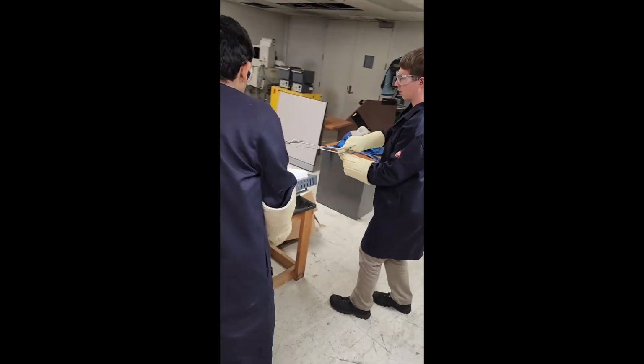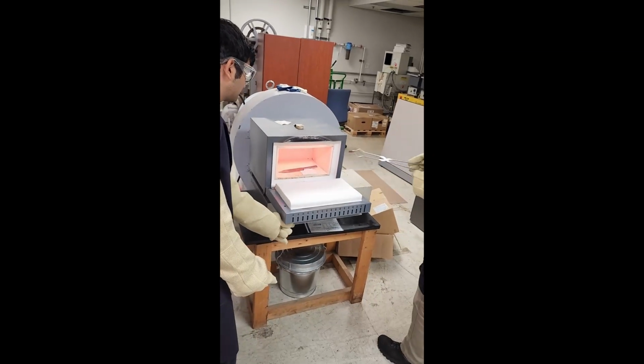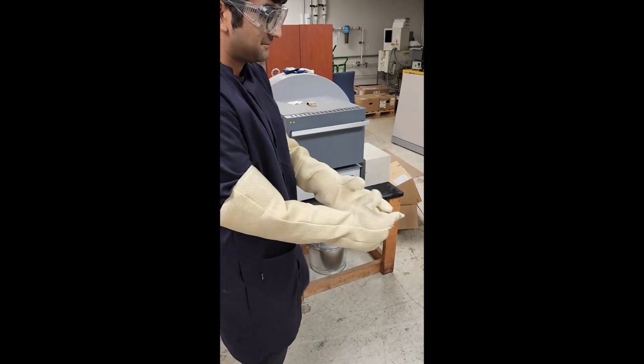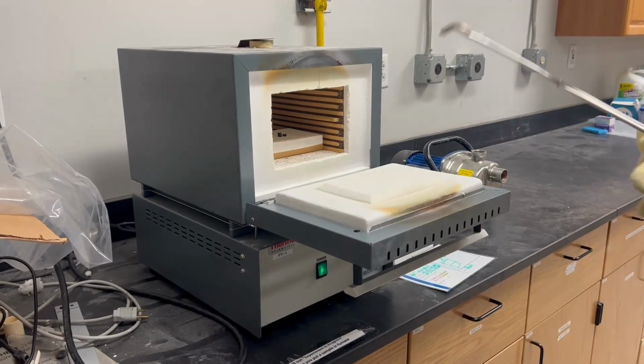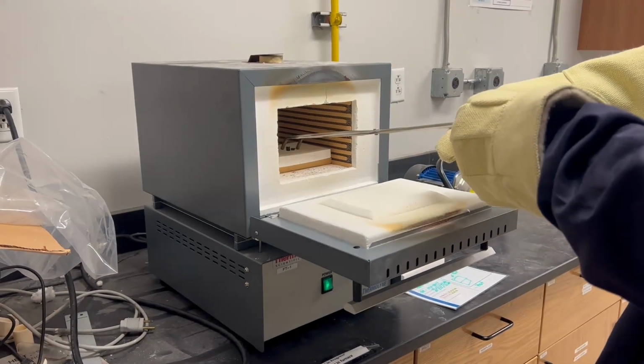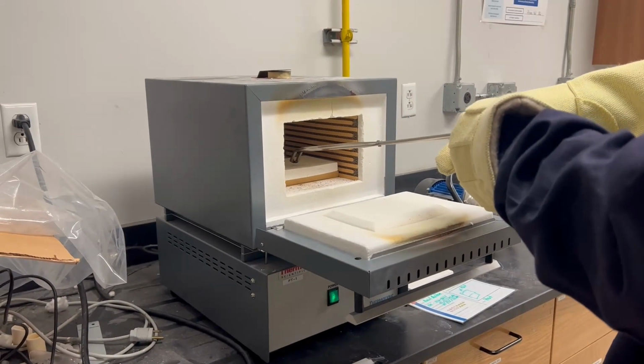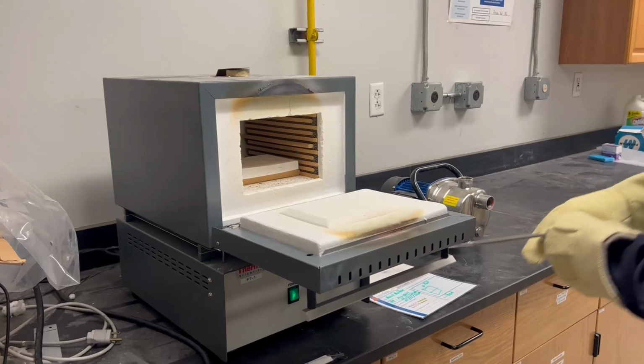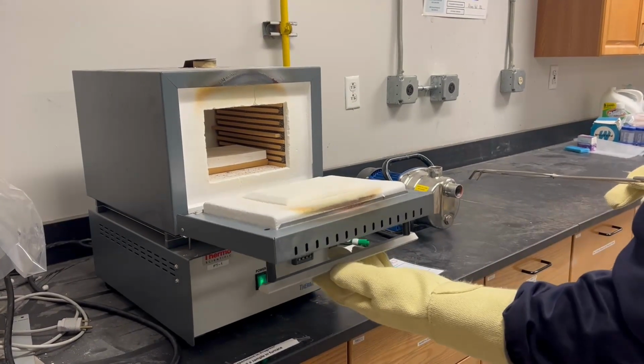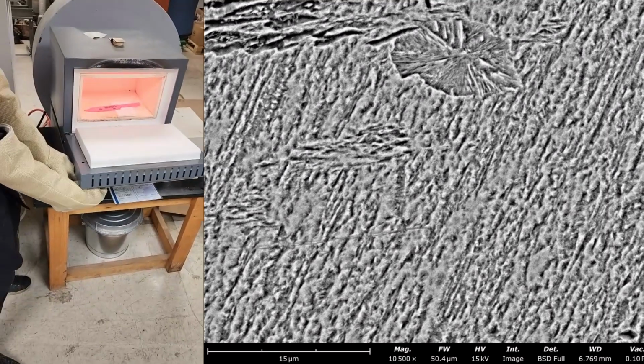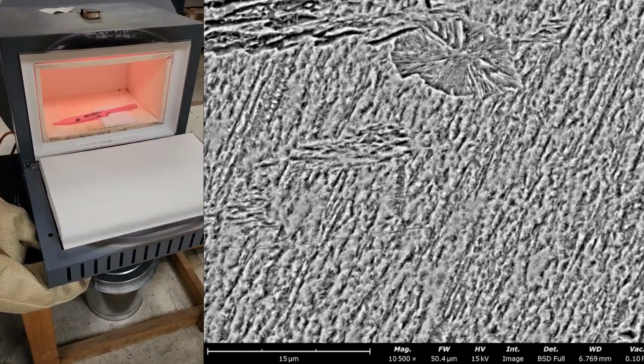As we moved into heat treatment, we wanted to see if the temperatures and times we researched would have the intended effects on the microstructure and material properties of our blade. To do so, we used 4 samples taken from the first billet to obtain scanning electron microscopy images at each step of the process, followed by Vickers hardness testing. The blade was first normalized above its austenitization temperature and air-cooled to reduce internal stress gradients.